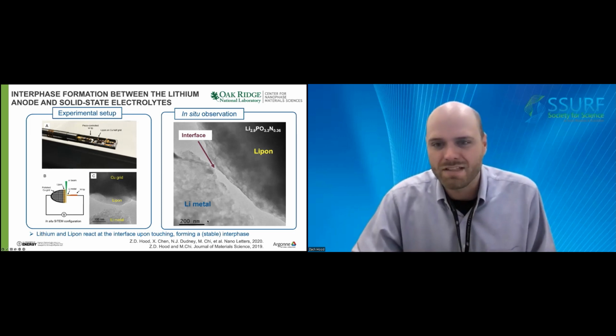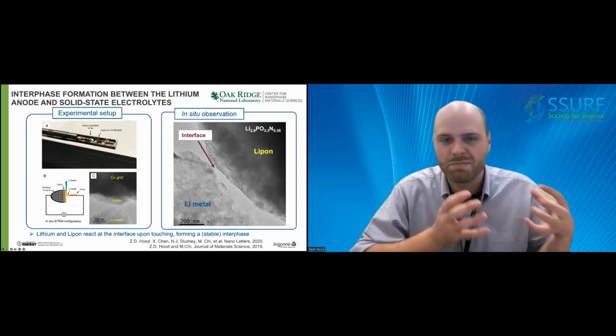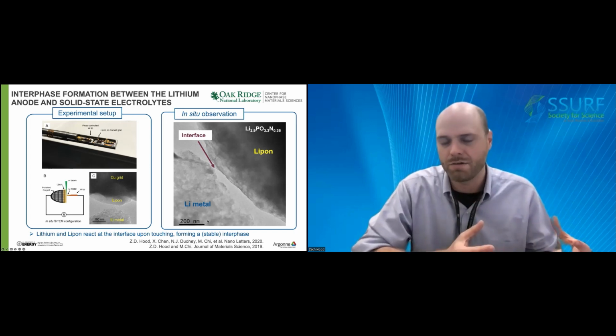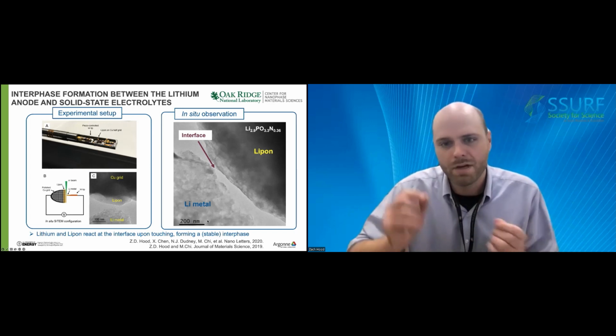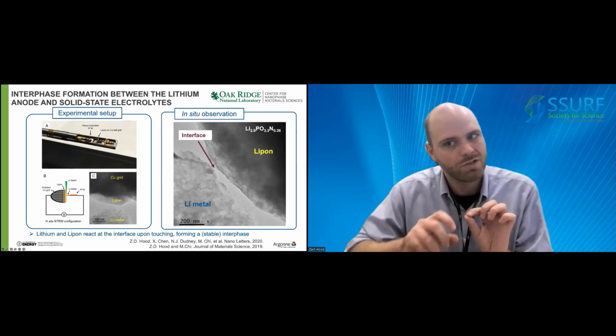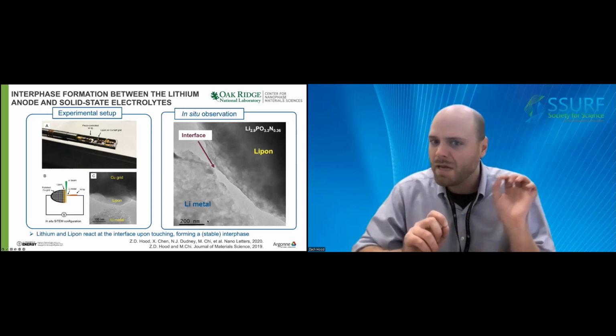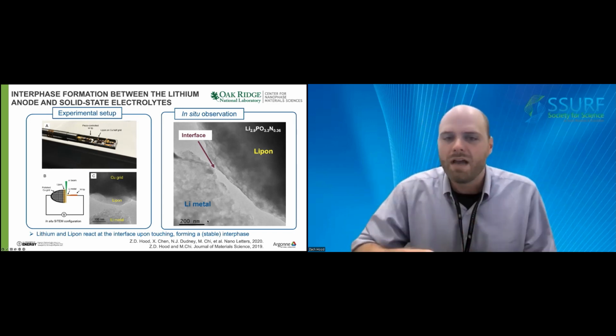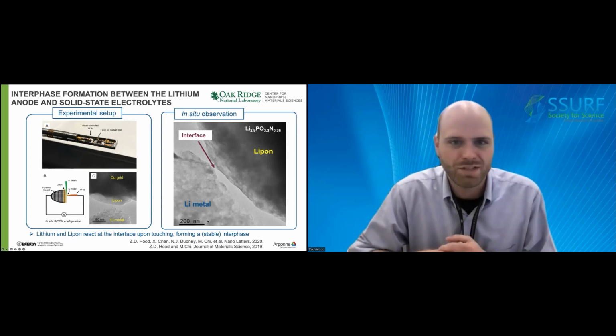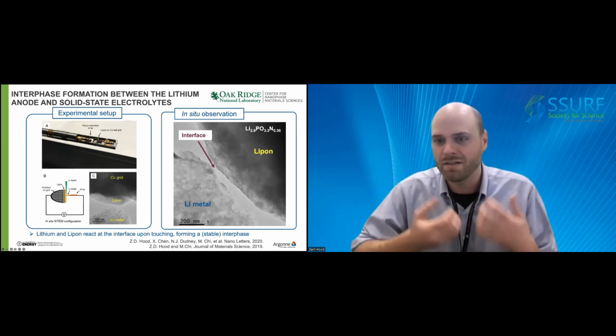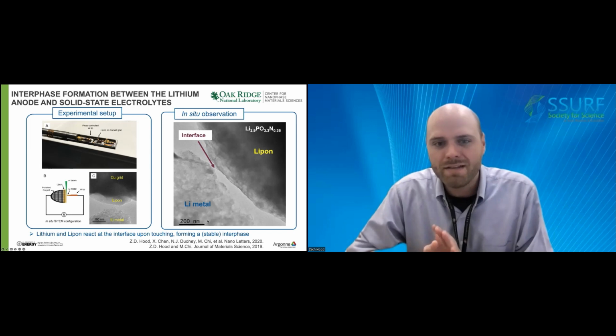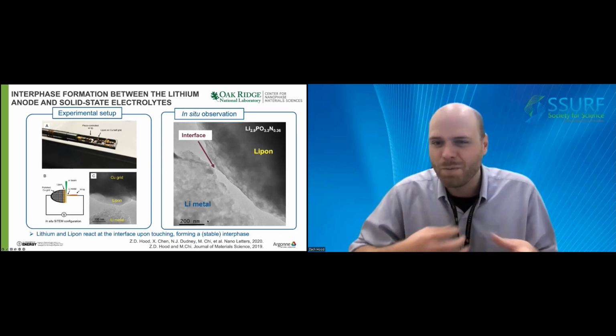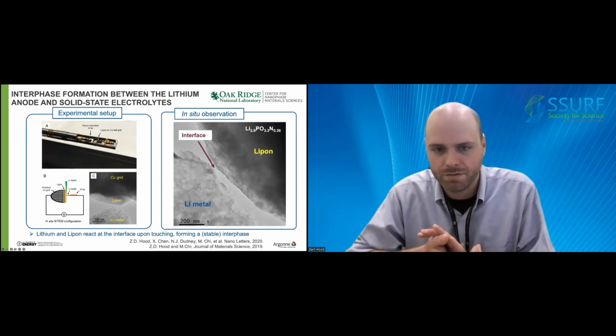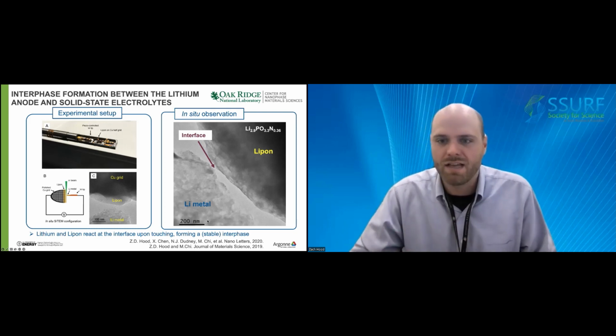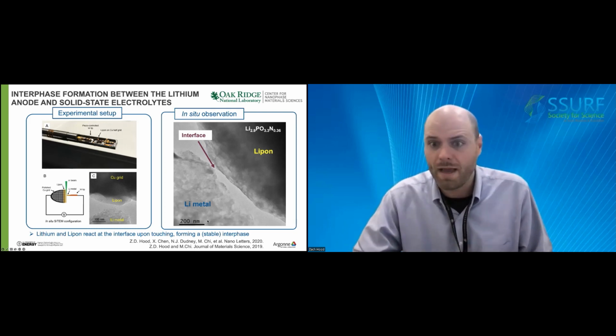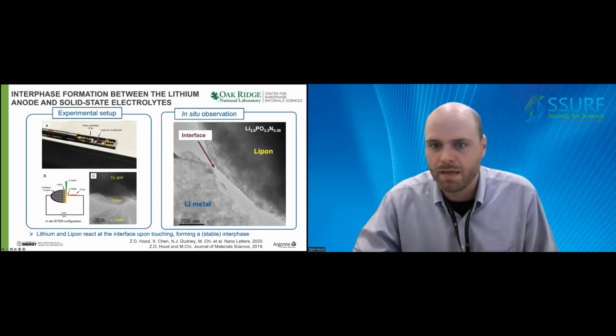So on the left-hand side of the slide, you can see the general experimental setup that was designed at Oak Ridge National Lab. Here, we deposited LiPON directly onto a polished copper grid and lithium metal onto a tungsten tip. After carefully transferring these materials into our electron microscope, we then set off to interrogate exactly what happens at this interface. On the right-hand side of the slide is a video of actually what happens in situ. So I'll play that now.